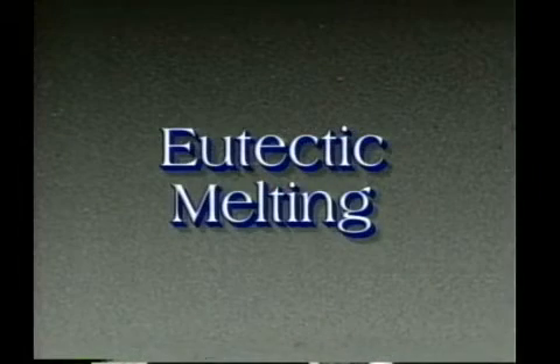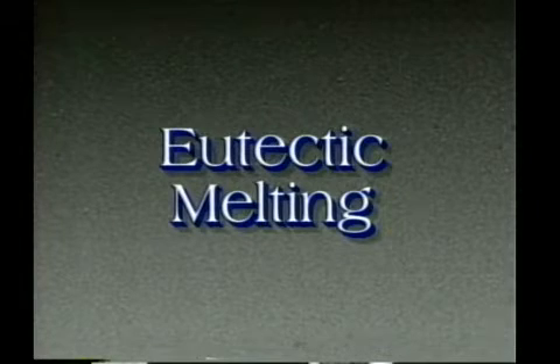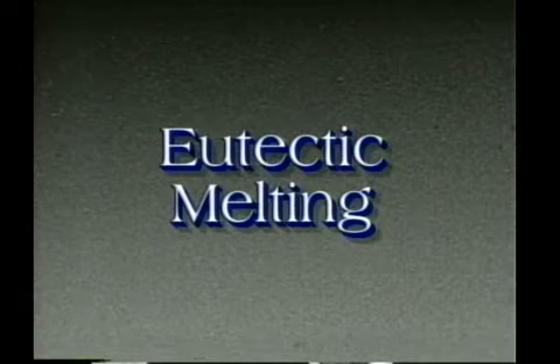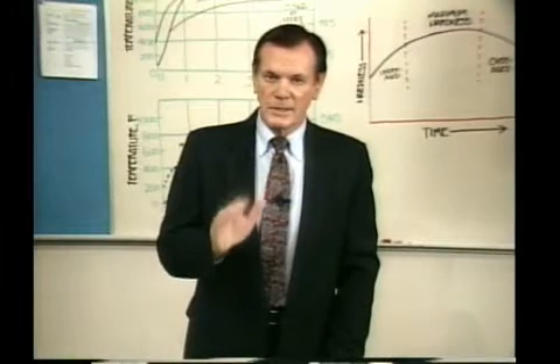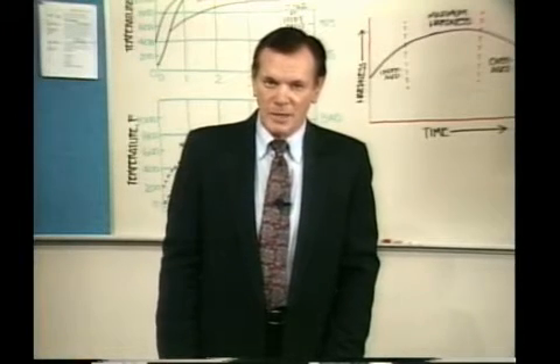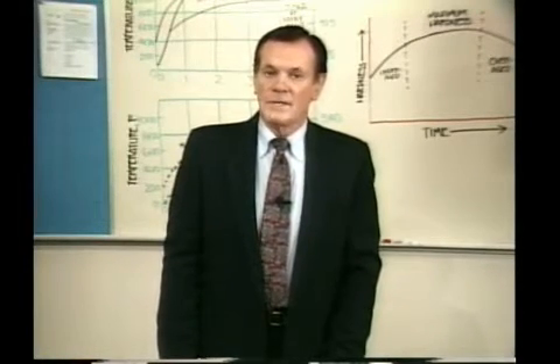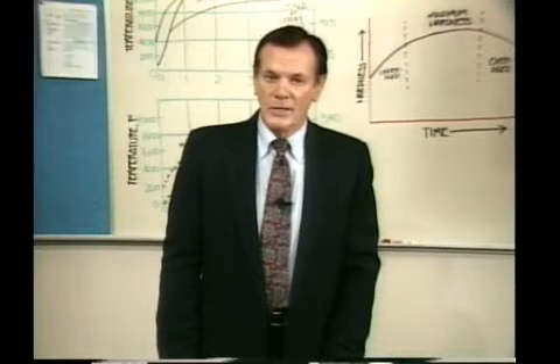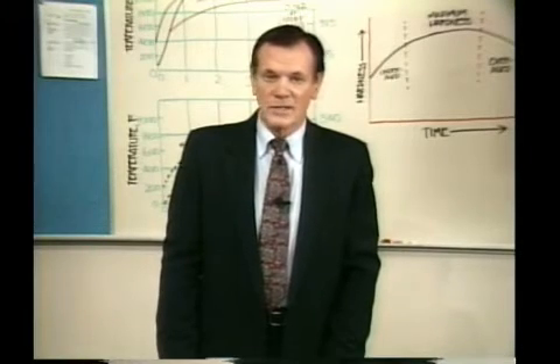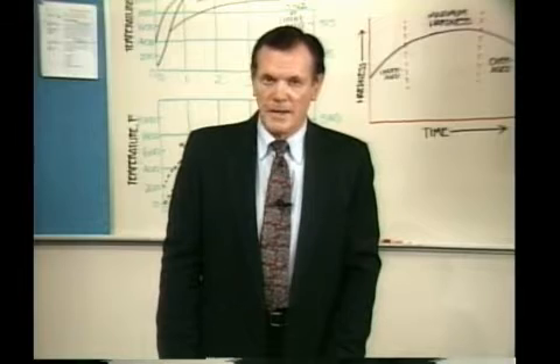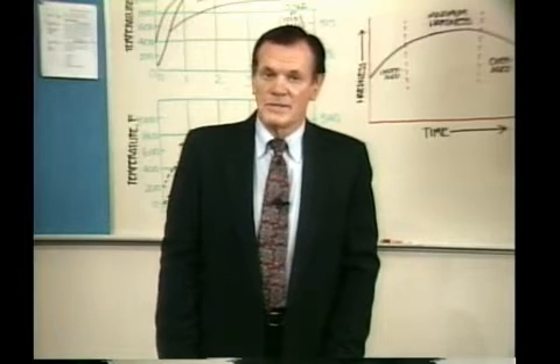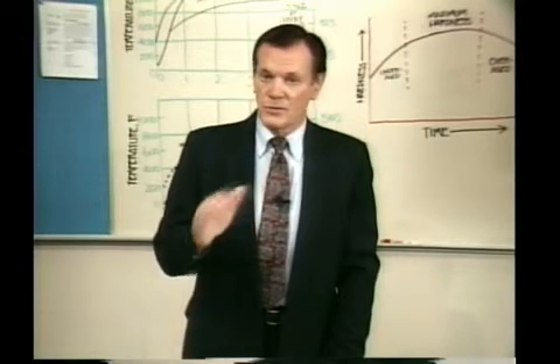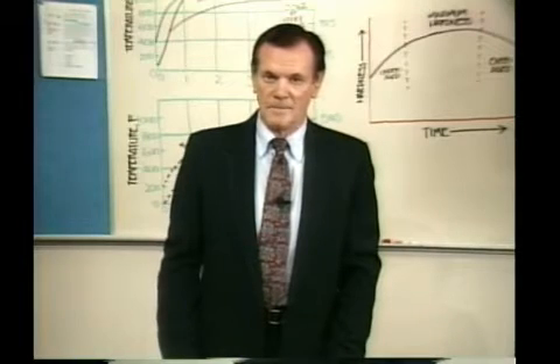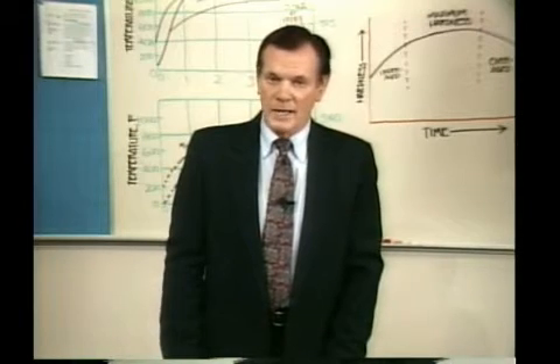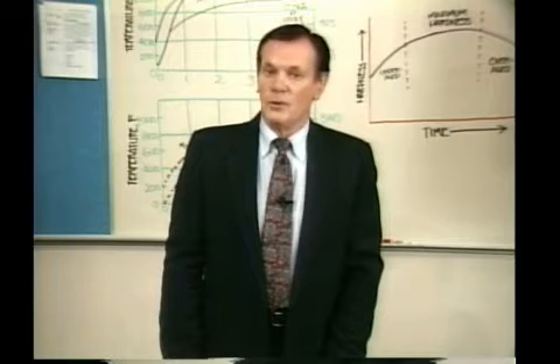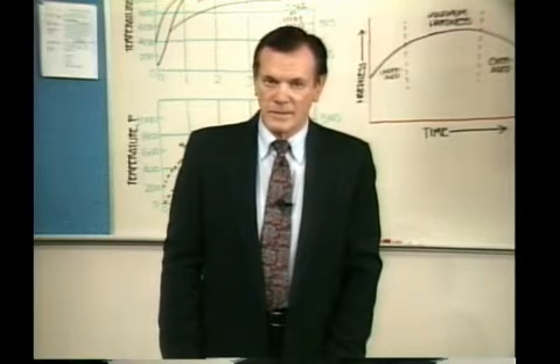Eutectic melting during solution heat treatment must be avoided at all cost. It is the most important consideration in the heat treatment of aluminum alloys. When this temperature is exceeded, intergranular networks of a brittle glass-like eutectic are formed. If extensive, this network may significantly decrease both the strength and ductility of the part. In addition, quench cracking is sometimes encountered when the normal solution temperature is exceeded.